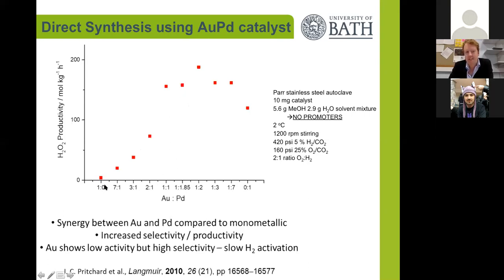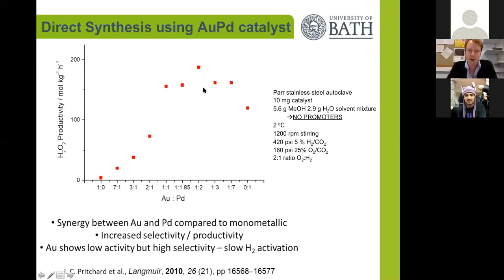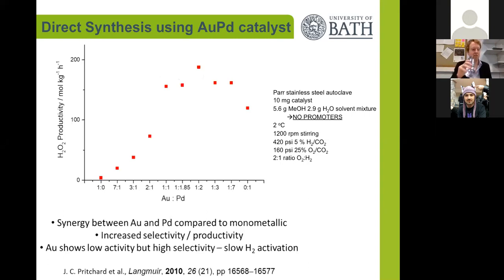Gold has very low hydrogen conversion but quite high selectivity, which leads to a low net productivity rate. Palladium-rich catalysts convert a lot of hydrogen but have much lower selectivity. The balance between achieving conversion and selectivity gives these observed volcano plots, and we wanted to see if this was true in an electrochemical system as well as a heterogeneous system.